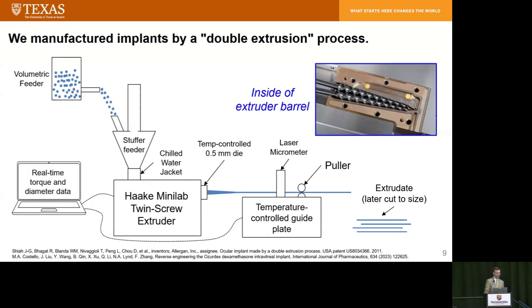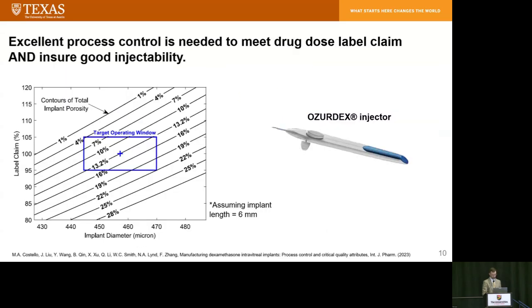And then the diameter of the extrudate is measured in real time by a laser micrometer directly next to the puller. Simultaneously, we measure the torque from the extruder in real time. So that's really critical to the process control, which I'll explain in the next slide. Measure the torque and diameter in real time. And then finally, once the extrudate is cooled, it's cut to the correct size. The process control is very critical for the quality of this product.